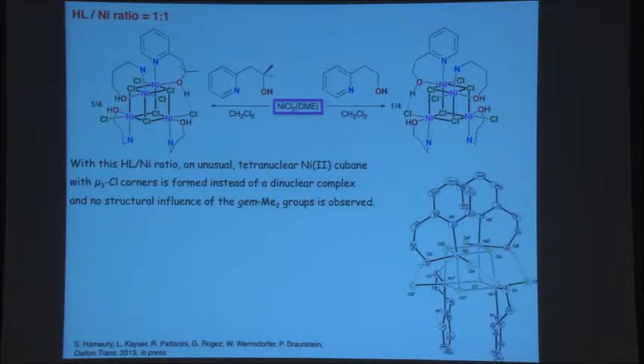Cubanes are ubiquitous in a number of systems, including in bioinorganic chemistry, iron cubanes, etc. It's a structural type which is well known. With nickel halides, surprisingly, very few, none to our knowledge, with triply bridging chlorides as corners in the cubane substructure. And that was established by X-ray diffraction here. So we see in both cases a similar structure. So in this situation, the gem-dimethyl group does not seem to influence the structure of the product, in contrast to what we've seen before. So very subtle differences you have to investigate first.